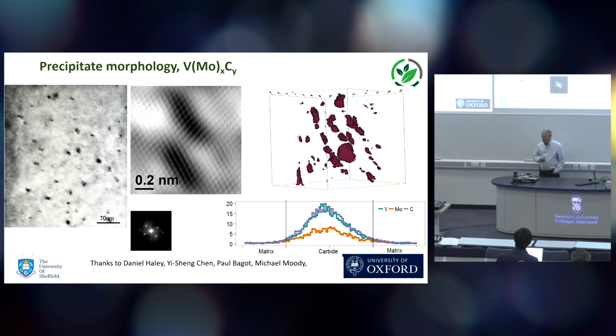If you look at the precipitate structure within it, here is the TEM image on the left, high resolution. You can see from the scale bar, the precipitates really are very fine, typically about 3 nanometers or thereabouts. This is atom probe, showing there's a really high number density, in this case of vanadium carbide, and here's the composition across one particular carbide, which has the vanadium carbide, but also molybdenum goes into those precipitates and modifies behavior.